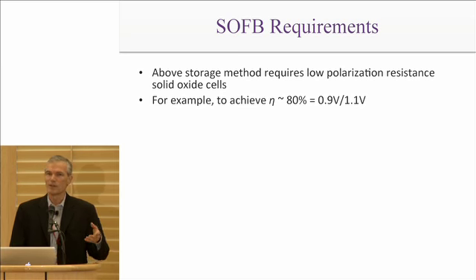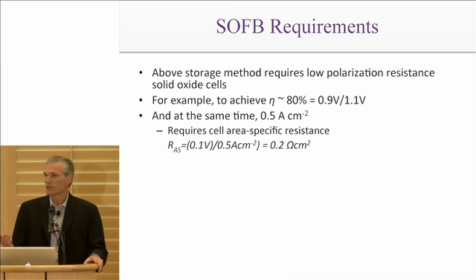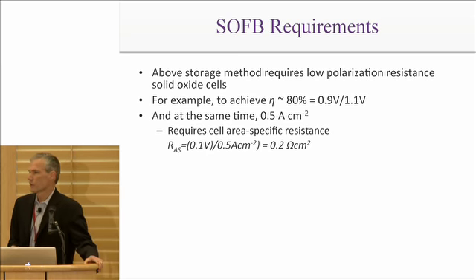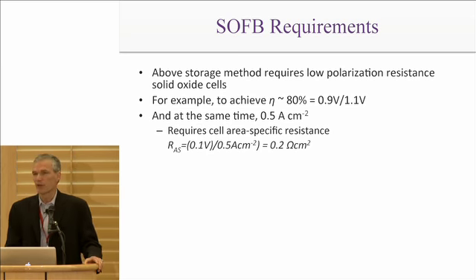Okay, so that means that the overpotential of the device that's operating at 0.1 volts, if we want to get a reasonable current density like half an amp per square centimeter, that means the resistance of the device has to be 0.1 divided by 0.5 or 0.2 ohm cm squared for the resistance. And this is, if you look at fuel cell literature, this is actually a fairly challenging number, but not totally out of reach by any means.